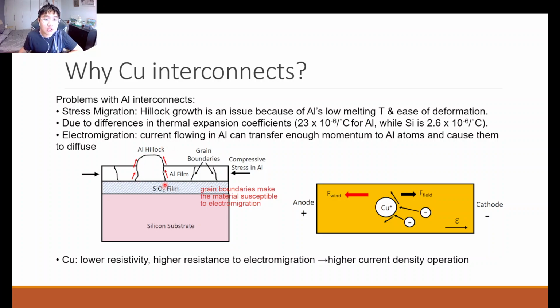In addition, there's also a pretty large difference in the thermal expansion coefficient between aluminum and that of silicon, as well as the other materials that are present in the semiconductor wafer. This mismatch of thermal expansion coefficients can cause distortions in the volume and geometry of the aluminum interconnects. This is especially the case because oftentimes a deposition of the metal is conducted at a different temperature compared to device operation, right? The metal is often deposited at a higher temperature, or an anneal is conducted at a higher temperature than room temperature, where your device is operating.